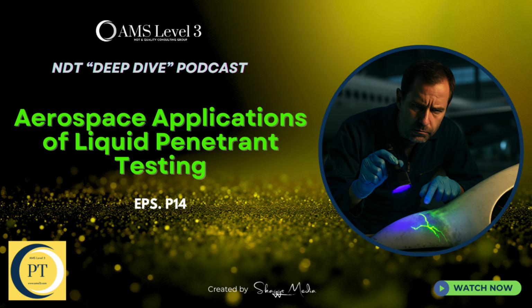The minimum dwell time, that's the time the penetrant soaks into the crack, is typically 10 minutes, but it can be longer depending on the part. And the maximum dwell time is just as important. If you go over 2 hours, the penetrant can start to dry on the surface, which really messes with the removal step. So you have to start over. You have to clean it and start all over again.